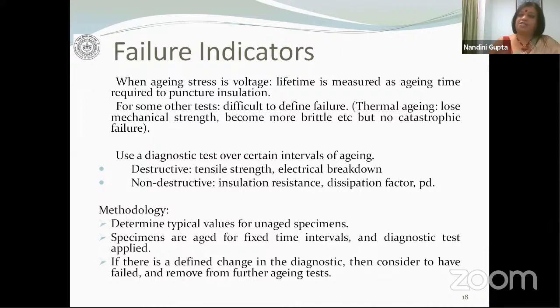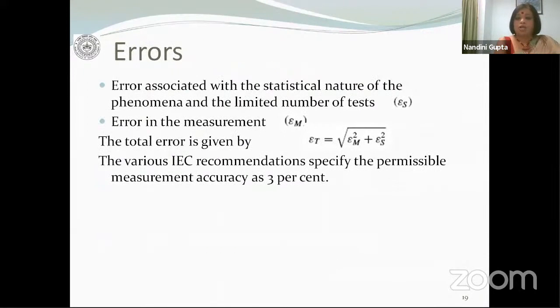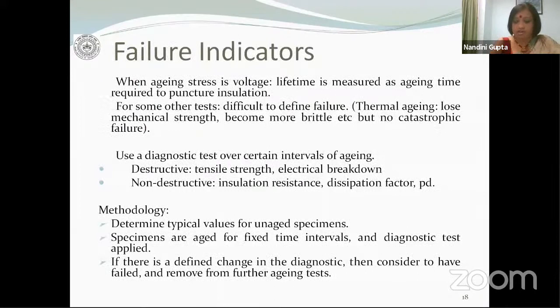Or with thermal aging, it may lose its mechanical strength. And very often when we use solid dielectric materials, we are not choosing a solid dielectric material just because it is going to provide me a high permittivity or a high dielectric breakdown strength, but it is also put in place to provide mechanical strength. For example, insulation in bushings, we need to provide mechanical strength. So therefore, what we would have to do is provide some kind of diagnostic test over certain intervals of aging. So there are certain tests which are destructive in nature, and there are certain tests which are non-destructive in nature. When we are looking at destructive tests, we can wait for the material to be destroyed. So the examples of destructive tests are measurement of tensile strength or electrical breakdown.